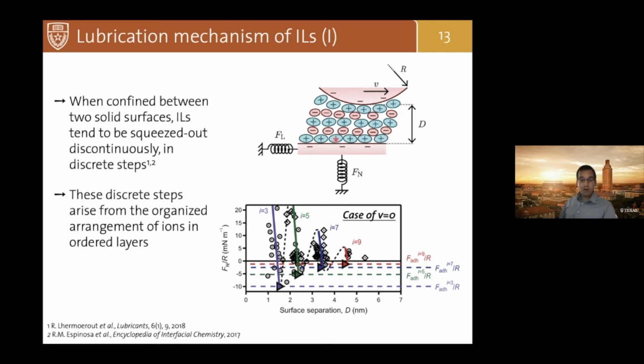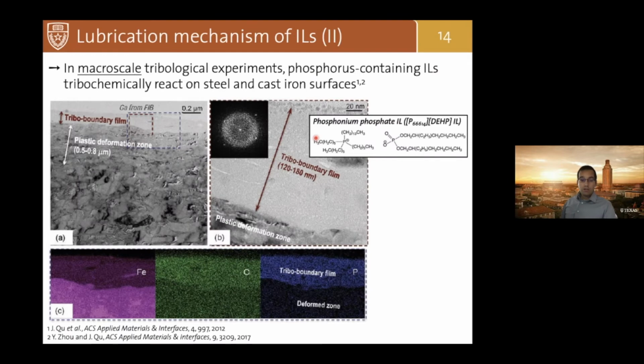Because of this squeezing out, or because of this rearrangement, people have basically proposed that this arrangement of the ionic liquid during the compression and confinement actually results in the lubricity of the ionic liquid. However, at the macro scale, a group led by Jun Qu from Oak Ridge National Lab clearly showed a while ago that ionic liquid actually reacts on surfaces, so a completely different mechanism. They create these layers, which you see on top of this steel.